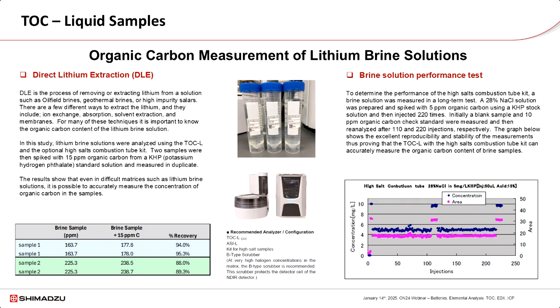In addition, a blank sample and a 10 ppm organic carbon check standard were measured initially before the 5 ppm brine solution, and then again in the middle after 110 measurements, and at the end after 220 measurements of the 5 ppm brine solution. As you can see in the results, this proves that the TOCL instrument is capable of accurately measuring the organic carbon of brine samples.